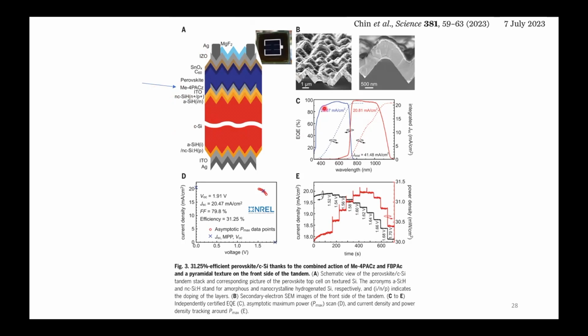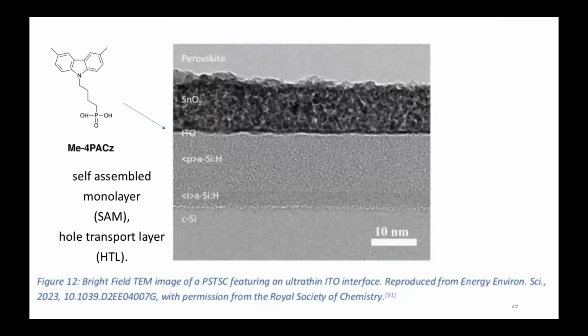You can also see that the structures that they use, the silicon, it has a pyramid structure. So that is a general trick in the silicon field, that you make black silicon, you make a pyramid structure that absorbs the light better. You get reflections, internal reflections. But here we have our monolayer on indium tin oxide. So this is a monomolecular layer of this molecule. It's a self-assembled monolayer, like we saw for our alkyl thiols on gold, and it transports the hole. So it transports positive charges.